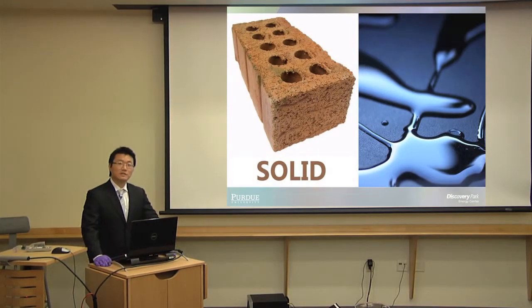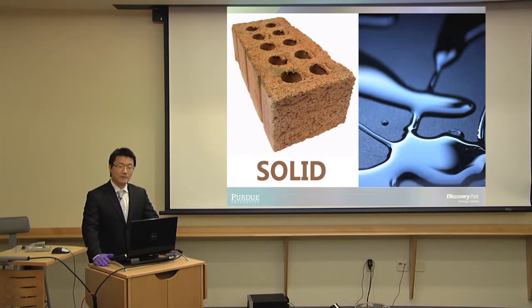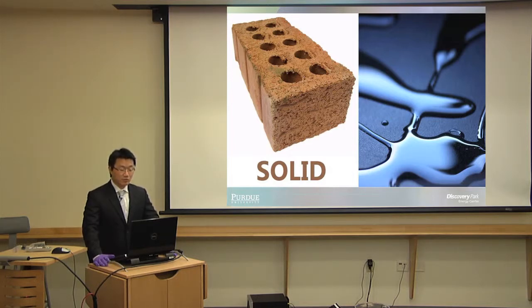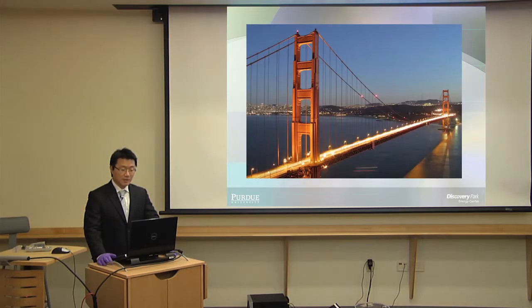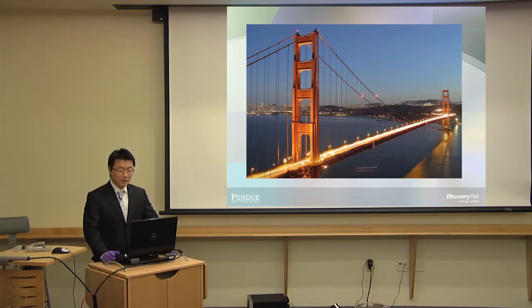Now let's learn about the mechanism. This alloy is composed of two phases: solid phase and liquid phase. The solid phase is composed of aluminum. The liquid phase is composed of three different metals — gallium, indium, and tin. This liquid metal has an important role. It works as if it is a bridge. It allows the aluminum particles, the solid particles, to travel around and react with water to produce hydrogen.